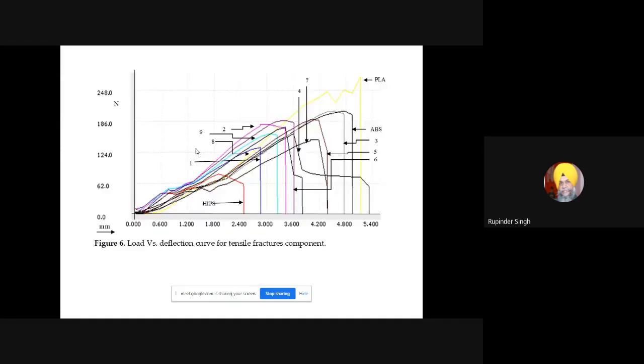Now you see over here, if I use this proportion as explained in experiment number 1, it must have a loss in the property, so that I can always correlate with my stress strain curve. In this, you can see for experiment number 1, I have a minimum area under the curve. So that means the strength of the part for curve 1, in which HIPS was on the top, PLA was sandwiched between the HIPS and the ABS, I must have a loss in the property.